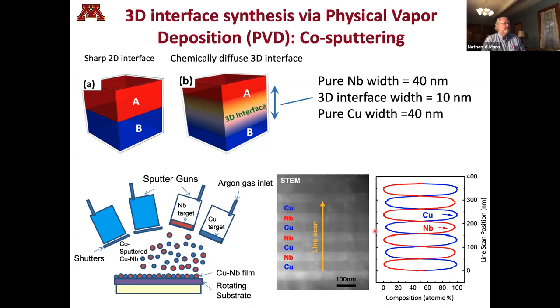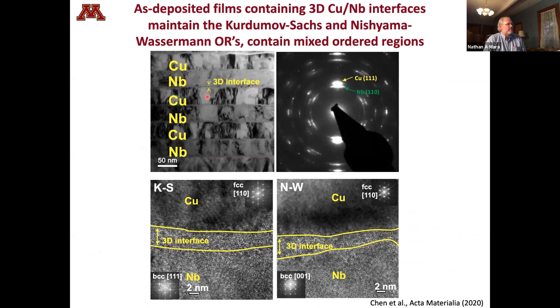When we look a little bit closer in the TEM, this is what we see. So you've got alternating layers of copper and niobium and copper and niobium, but you can make out these kind of gray blurry regions between the two. That's our 3D interface. You zoom in on those, do a little high-res TEM. They're not just an amorphous material. It's not just making glass. You're making a mix of ordered regions, which you can see here indicated by the lattice fringes, and then also these kinds of oatmeal-y looking regions, which don't have quite the same degree of ordering. You can see this also, we get another orientation relationship called Nishiyama-Wassermann, which is very close to what you see in Kurdjumov-Sachs. It's only about 7 degrees off or so. So very, very similar results there.